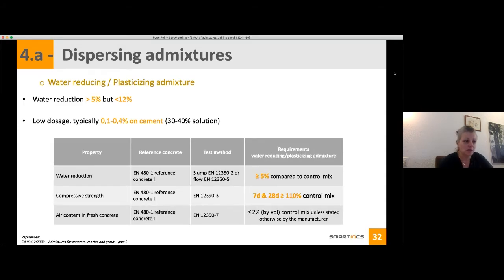Here are the requirements, still according to the norm. The first requirement relates to the water reduction, and as just mentioned, more than 5% compared to a control mix. But you also have some requirements relating to strength. So you can reduce water, but it also means that your 7 day and 28 day strength should be at least 110% of your control mix. This is a requirement that you will find for all admixtures, besides air entraining agents, is the air content in your fresh concrete. It can increase a bit, but no more than 2% compared to a control mix.